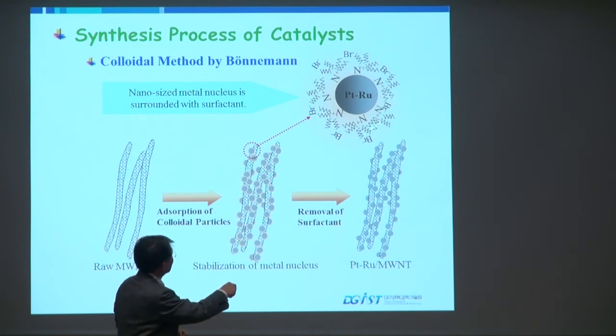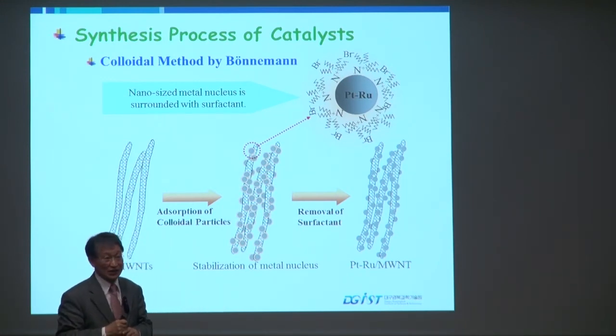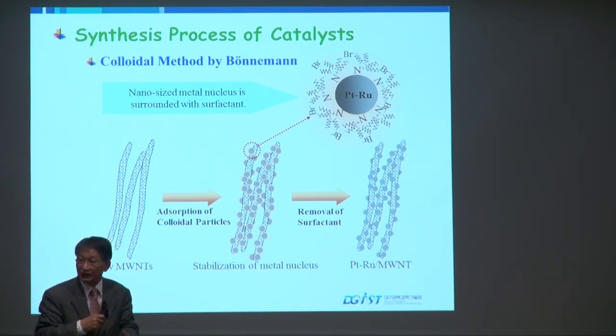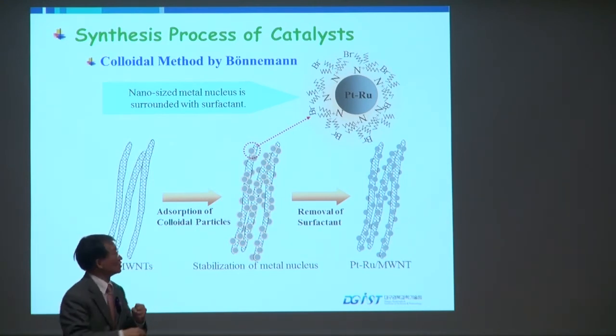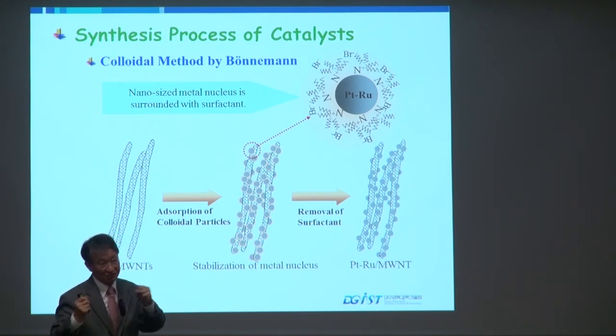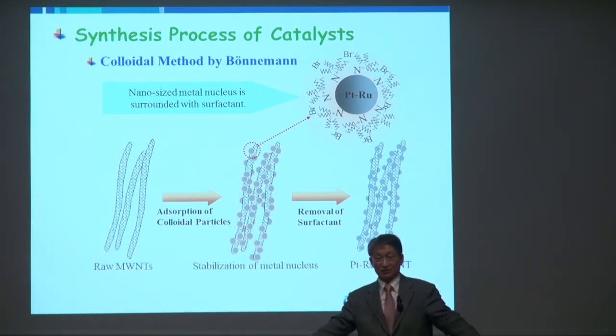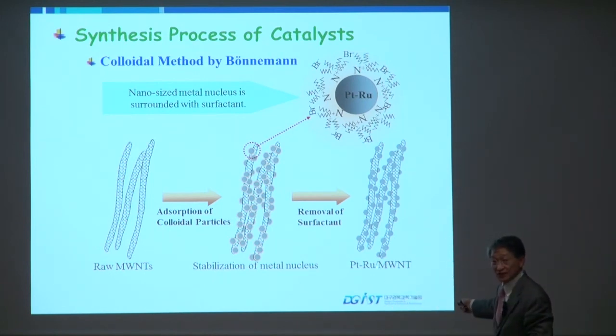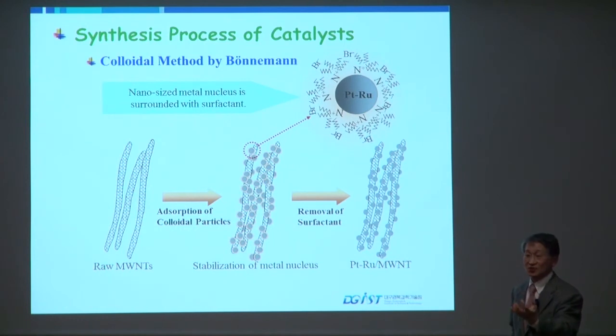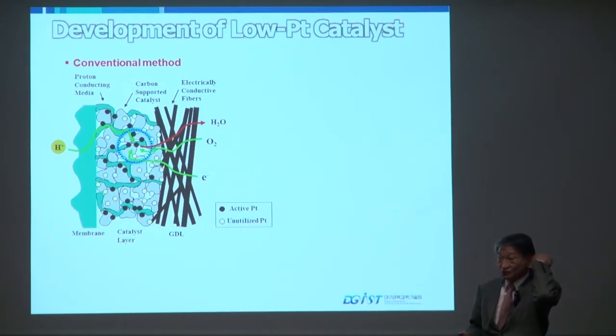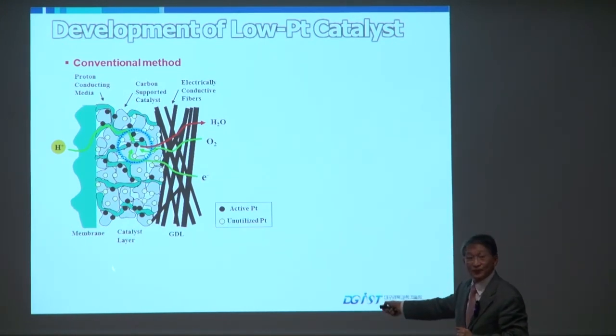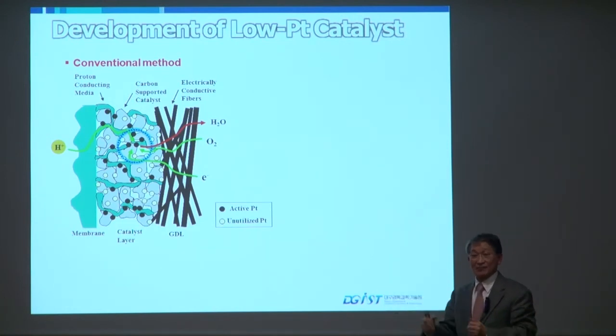Then there is a surfactant shell outside. This organic part is easily adsorbed on the surface of carbon nanotubes. And after this, you heat it up to remove these organic shells away, about 300 or 350. Then the organic part goes away, and the metal part remains on the surface. So you have a very good homogeneous dispersion of catalysts on even carbon nanotubes. Then after you prepare this catalyst, you mix it with carbon and make a slurry, then apply it on top of the gas diffusion layers.